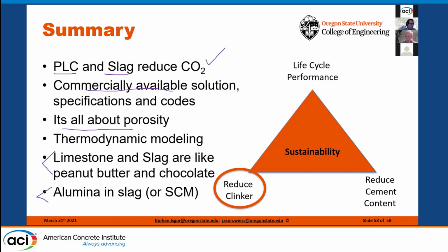And it says silica fume seems to do better than expected. I think one of the reasons that the silica fume is doing well in the system is it's reacting with our calcium hydroxide in the system, which is what we would expect to have in those cases. The slide showing a number of different mixtures showed slag and ash mixtures, where the slag performance was significantly higher than ash. What was the alumina content of the ash? If the alumina content of the ash is higher, but the performance is lower, how is that explained?